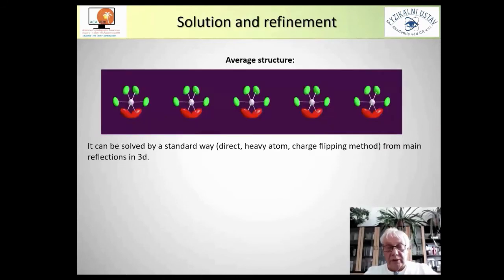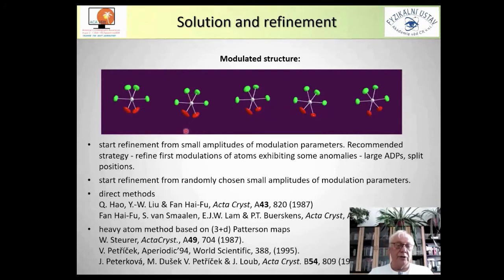For a very long time, for solution and refining of modulated structures, we were first starting with the so-called average structure. This can be solved in a standard way using only main reflections. Of course, then the structure is not describing modulation, but we have some average structure where, instead of different positions from cell to cell, we usually have large temperature parameters, or for occupation modulation, from time to time we also have split atom positions.